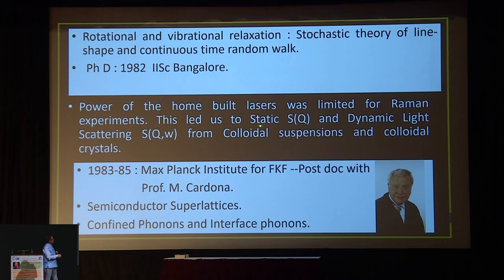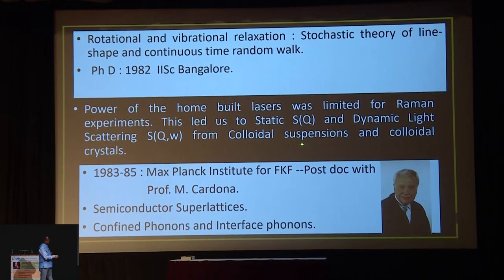We started looking at alternate physics which could be done with these lasers, and that led us to soft condensed matter, where we measured the structure factor S(Q), where Q is the wave vector transfer, and dynamic light scattering from the intensity-intensity correlation from colloidal crystals and colloidal suspensions.